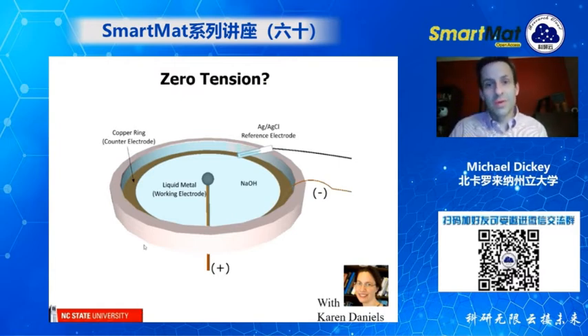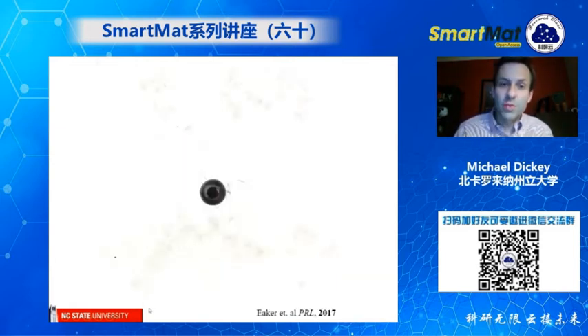So we did this experiment with Karen Daniels, and the experiment again consists of a droplet in a little dish with sodium hydroxide. That basically dissolves off the oxide, which is important because it allows the metal to flow as we apply this oxidizing potential. And we have a counter electrode that goes around the outside. So at just the right conditions, this is what we see.